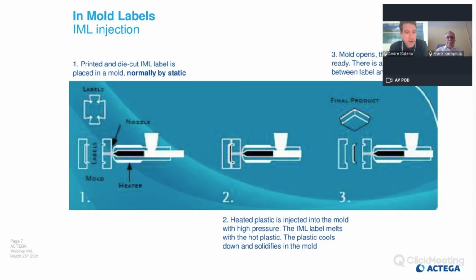The second method, very popular in Europe, is IML injection. Here you also have pre-printed, die-cut labels. They are put inside the mold using static. That's a really big difference to blow molding. This mold will be closed. Hot plastic will be injected into the mold at about 240 degrees Celsius, which is about 400 degrees Fahrenheit. This plastic will take the shape of the mold. It will melt with the label, the mold will cool down, and you have the final product.